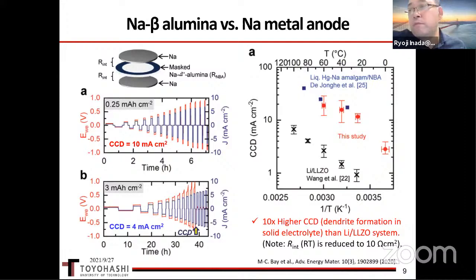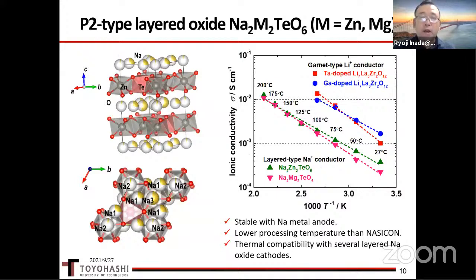Okay, this is the last slide of my presentation. We are now focusing on the layered type sodium solid electrolyte, MTO, as shown here. Although the conductivity of this material is slightly lower than NASICON and sodium beta alumina, this material is stable against sodium metal and its processing temperature is much lower. And recently, we found that several layered sodium oxide cathode materials are thermally compatible with this material up to 700 to 800 degrees C. We are trying to fabricate solid-state batteries by a simple co-sintering process now. That's all. Thank you very much for your attention.